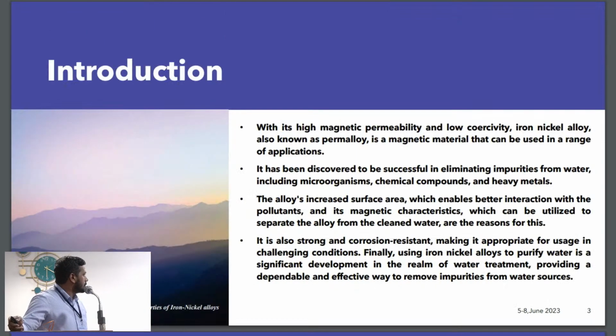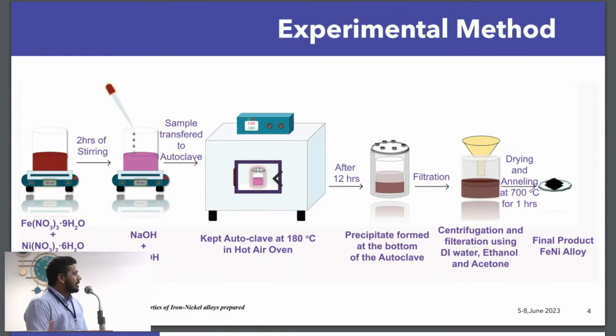My topic is synthesis, morphology and the magnetic property of the iron nickel alloy prepared by hydrothermal method. I prepared iron nickel alloy by hydrothermal method. Initially, I mixed iron nitrate and nickel nitrate in deionized water and stirred for 2 hours. After that, I added catalyst NaOH and NH4OH. After mixing it thoroughly, I transferred my sample to an autoclave, and the closed autoclave was kept in a hot air oven for 12 hours at 180 degrees Celsius. Then after natural cooling, I decanted, filtered, and dried my samples.